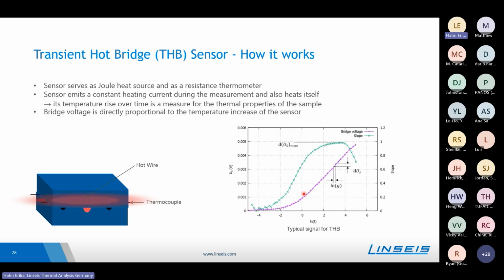So we will have the bridge voltage, which is rising with time. For the evaluation, we look at the derivative of that, so we look at the slope. The thermal conductivity can be extracted from this turning point where the slope changes. The thermal diffusivity can be determined based on this decay of the slope after the maximum. The QSS sensor and the hot point sensor work according to the same principle, but the evaluation and the measurement curve just look different.